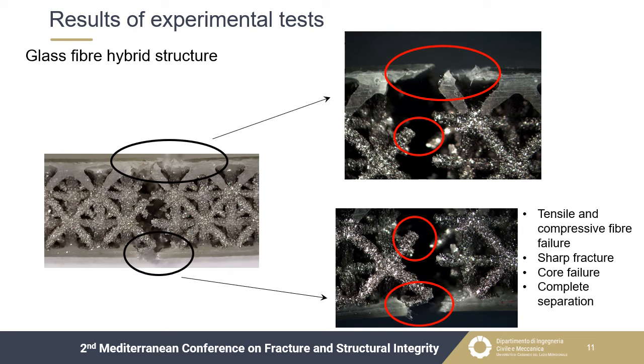In the last specimen, the glass skin one, the total failure of both the skins and the core was observed. In fact, after the test, the specimen was split into two halves, and this explained the reason why a sudden load drop till zero was found. However, in this case, the debonding of the skins was not observed.